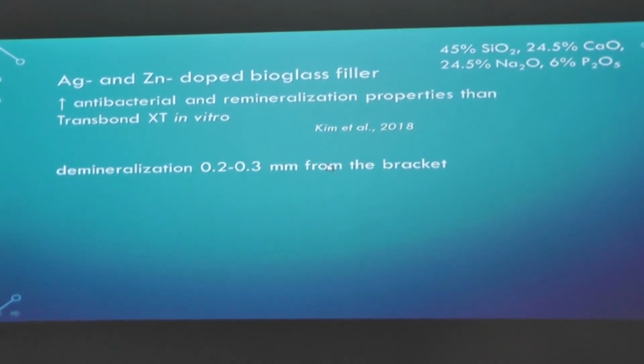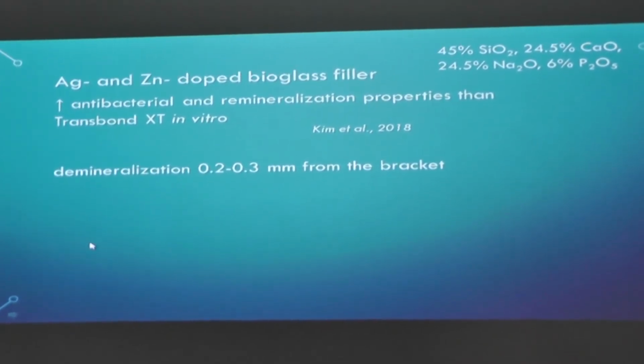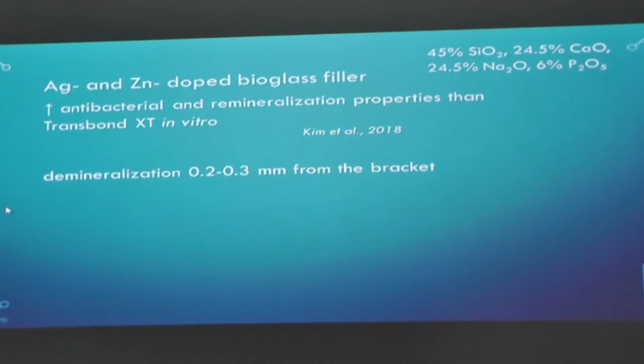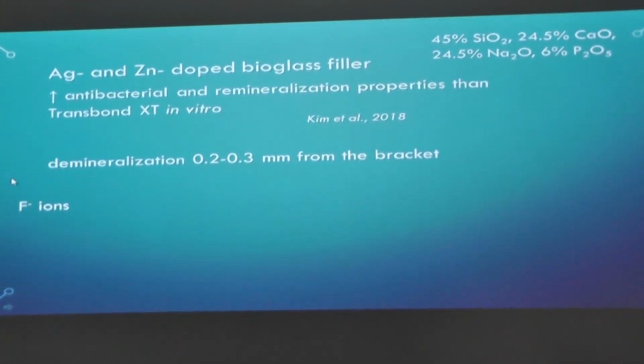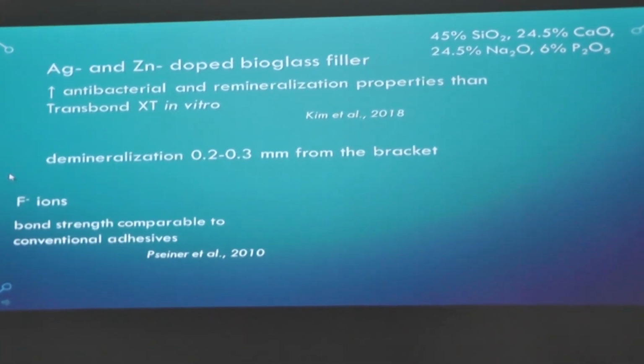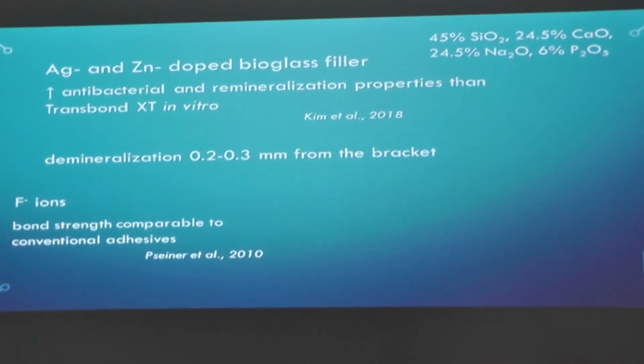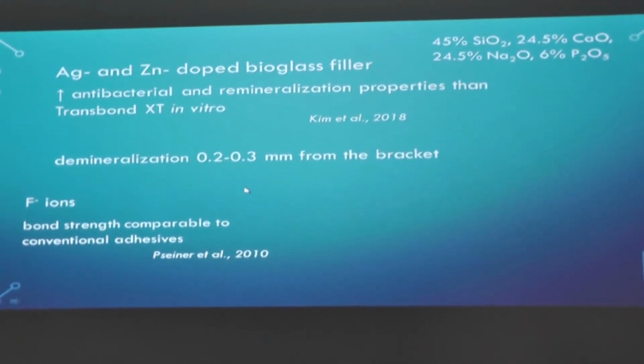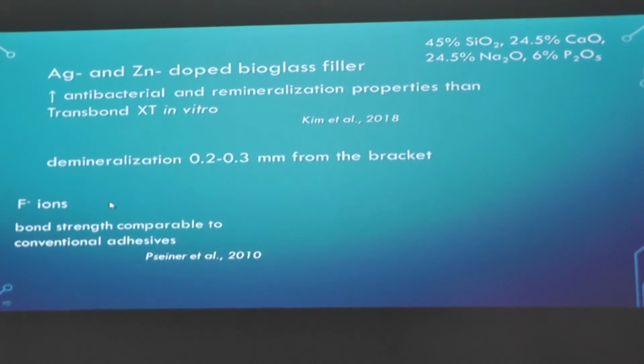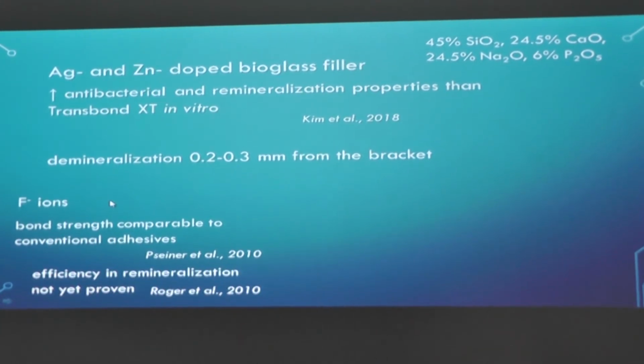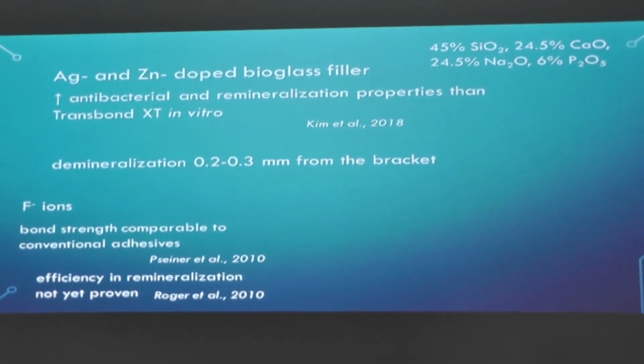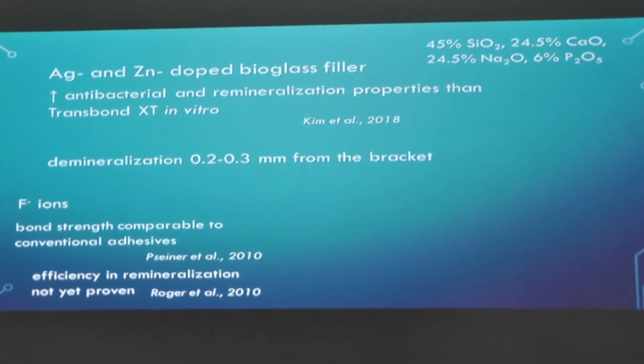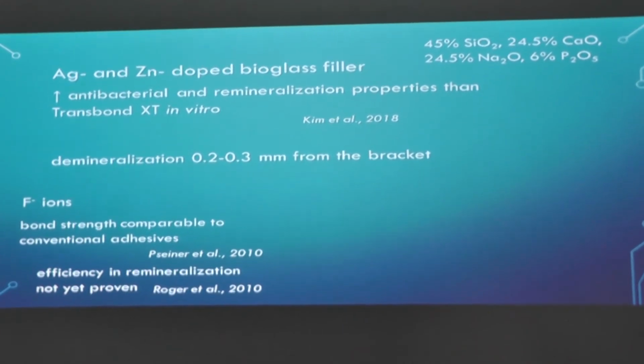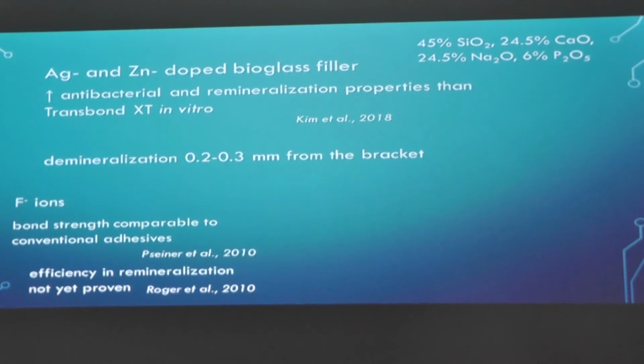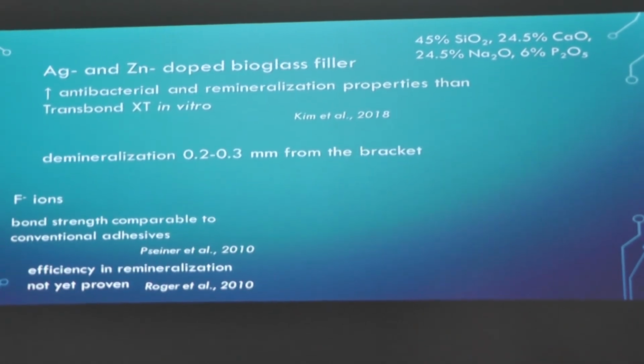Clinically this is not a significant result, and that is a problem with most of these in vitro studies. And also fluoride ions have been added to adhesives for 20 years, and they showed bond strength that was comparable to conventional adhesives, but their efficiency in remineralization is not yet proven, because it is one thing if you get hard enamel in vitro, but you have to prove this clinically, and this has not been managed yet.